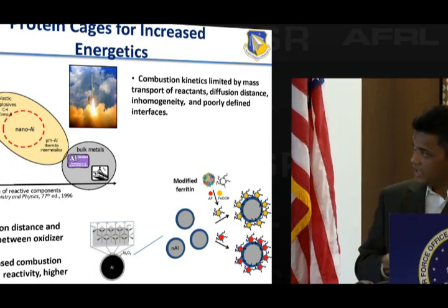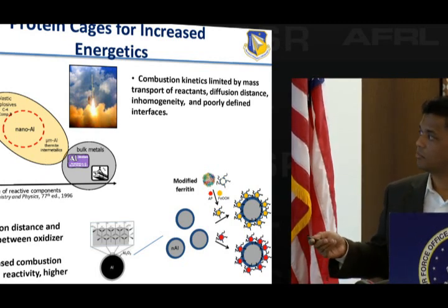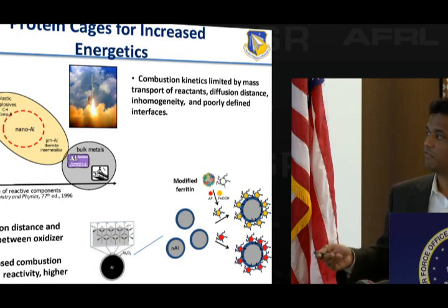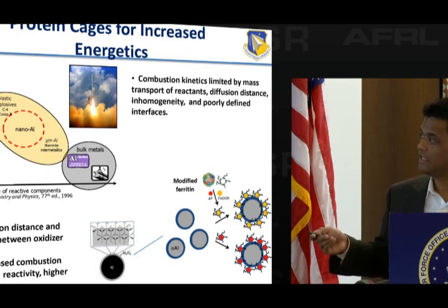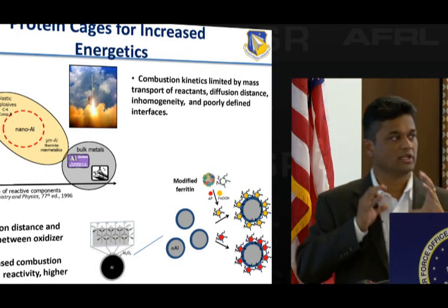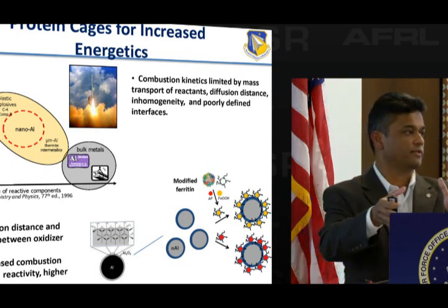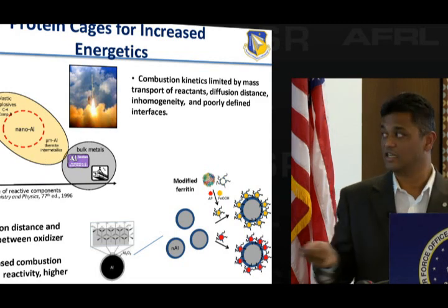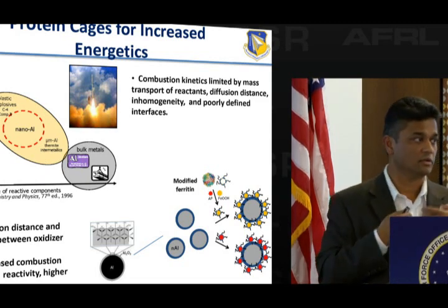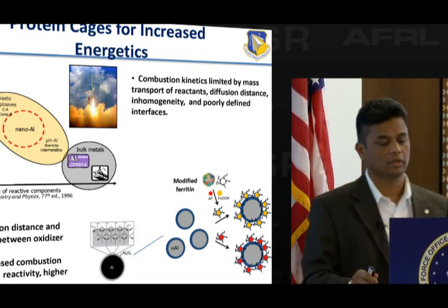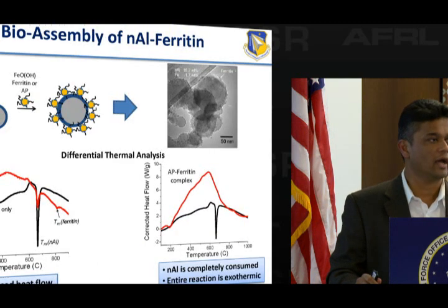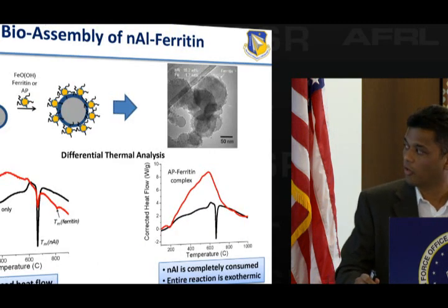So the crazy idea we had is to engineer the surface of the ferritin or apoferritin to have chemical ligands on the surface that like the surface of nanoaluminum. The aluminum particle has a thin oxide layer, so the idea is to bind to that oxide layer through the ferritin cage, and the ferritin is what will deliver the oxidizer to the surface, whether it's iron oxide that is inherent to the ferritin, because everybody has ferritin, it's just a way of sequestering excess iron in the body.